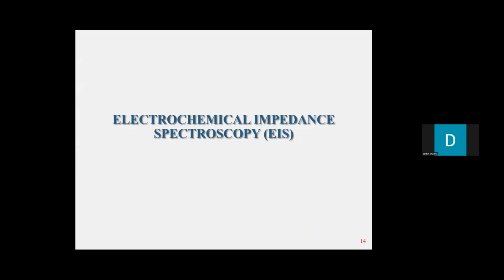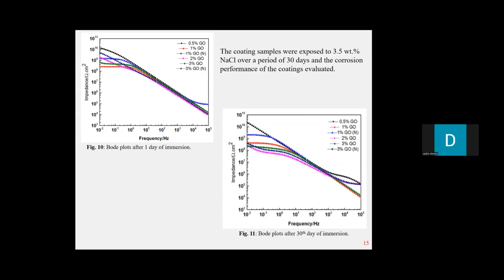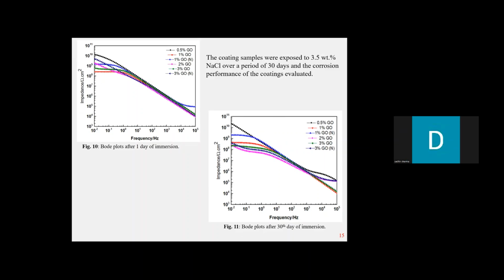So for the EIS, electrochemical impedance spectroscopy, the coatings were exposed to 3.5 weight percentage NaCl, which is basically seawater conditions, over a period of 30 days, and then the corrosion protection performance of the coatings was evaluated. Basically, you place a PVC tube on the metal substrate, and then you leave it for 30 days. Okay, so let's look at figure 10. These are the Bode plots for all the coating systems after 1 day of immersion. And among all the coating systems, the 0.5 weight percentage GO exhibited the highest result up to the 30th day of immersion, as illustrated in figure 11.